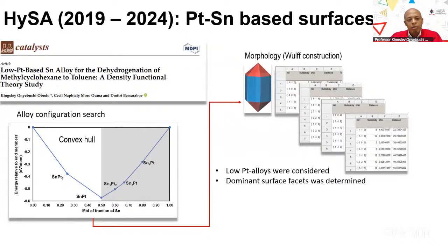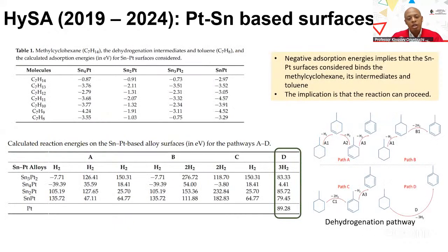Another work we did lately, as part of an EU project, was to look at how we can form alloys. Now we've looked at small concentrations of tin or different elements. Can we form alloys of these? Can we use these alloys to improve the performance of this catalyst for the dehydrogenation reaction? All of this was done using density functional theory as a computational approach. The first thing is, will all of these molecules actually stably adsorb? We found that they will stably adsorb on the surface.